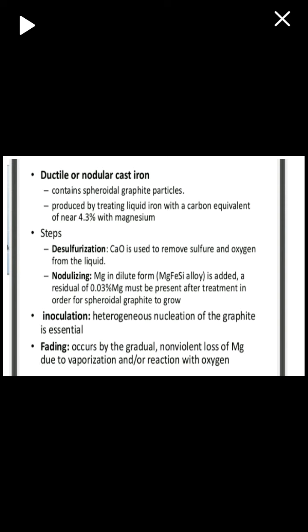Ductile or nodular cast iron contains spheroidal graphite particles produced by treating liquid iron with a carbon equivalent of near 4.3% with magnesium. Steps: desulfurization. Calcium oxide is used to remove sulfur and oxygen from the liquid. Nodulization.